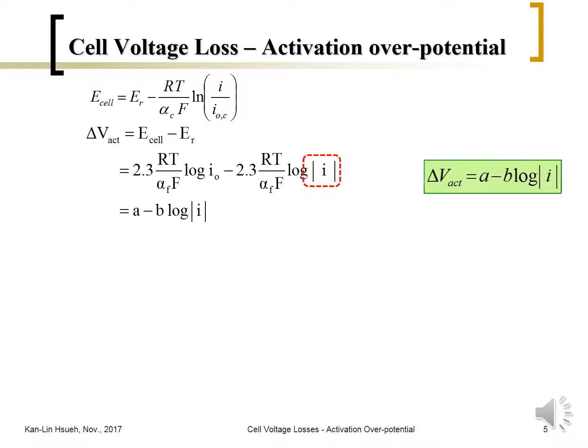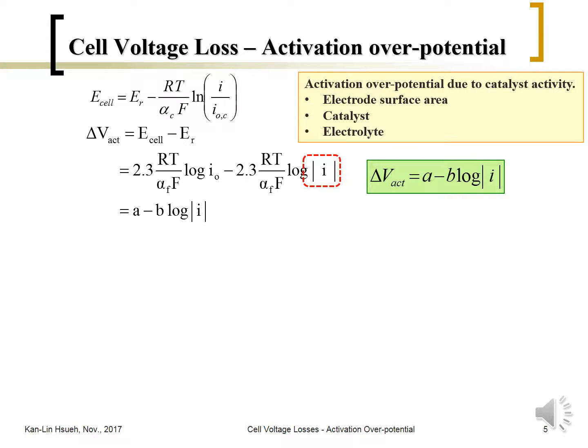The activation cell voltage loss is simplified as ΔV_act = A − B·log|I|. This activation overpotential is due to catalyst activity, which is attributed to the electrochemical surface area. A catalyst with higher surface area increases I₀, reducing activation overpotential. It also depends on whether you use a more or less active catalyst, the electrode composition, and conditions such as pH.